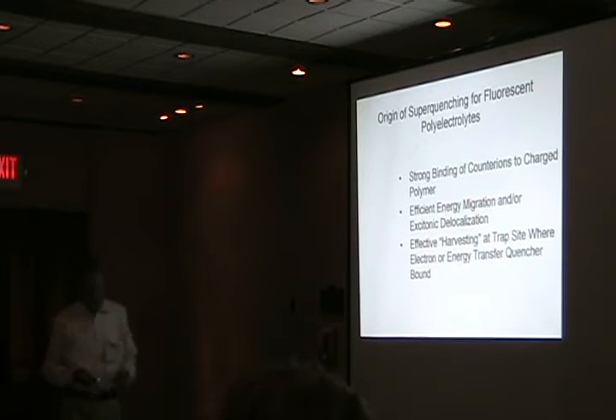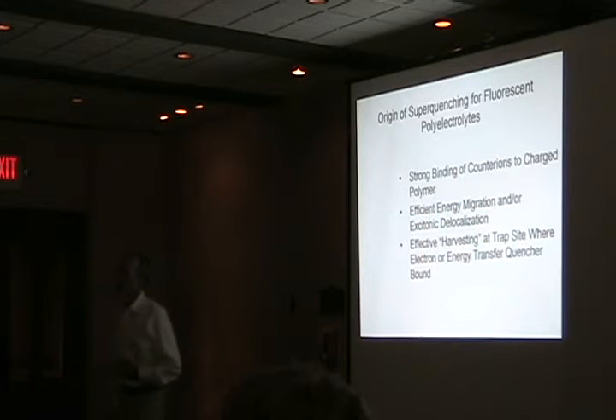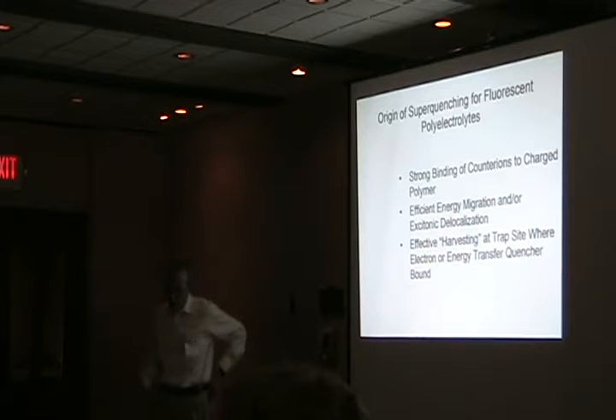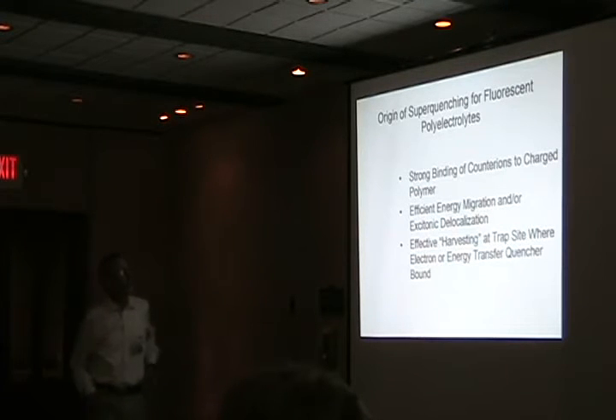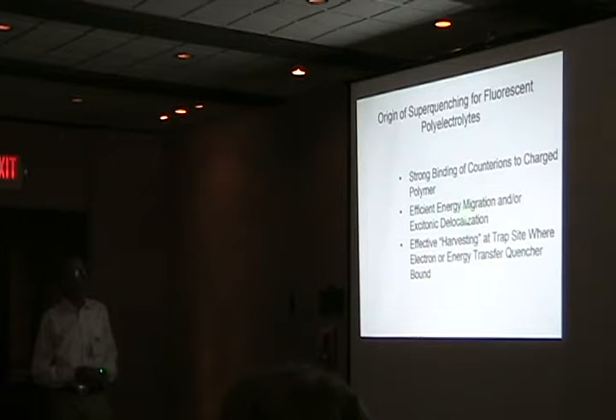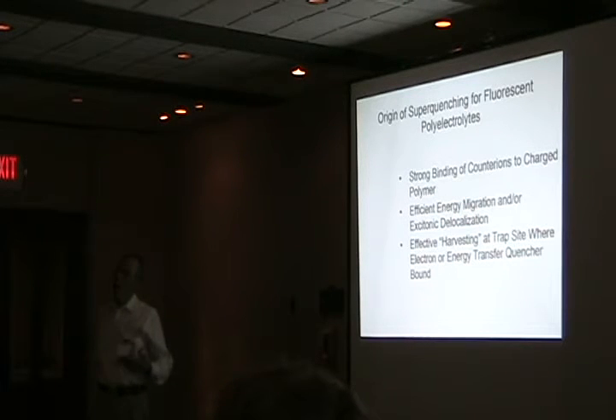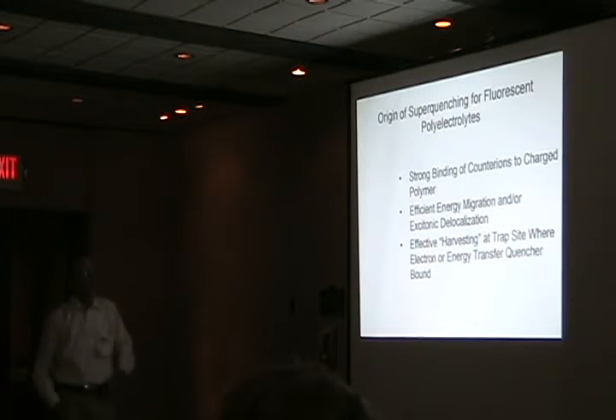But let's talk a little bit about super quenching. What does it do? Well, first of all, we have the strong binding of a potential quencher counterion to the charged polymer. And we believe again that there's efficient, or relatively efficient, energy migration or excitonic delocalization in the polymer. And I'd have to say from our work we have very similar results to what Paul talked about, that in general the excitation seems to be delocalized over something close to 100 to 500 polymer repeat units.